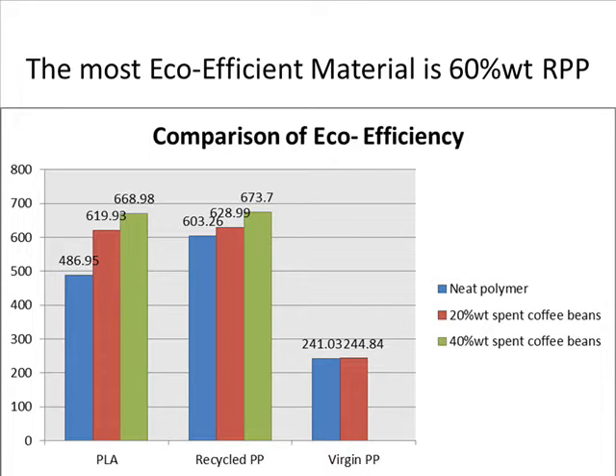However, with a compromise in the tensile and impact strength of the materials, although polylactic acid has better mechanical properties than recycled polypropylene, its carbon footprint is higher, resulting in the eco-efficiency of the bio-composite compounded with 60% by polylactic acid and 40% by spent coffee beans being slightly lower than the bio-composite made from 60% of recycled polypropylene and 40% of spent coffee beans. Nevertheless, as the life cycle inventory of the polymers was only considered from cradle to gate, the results might differ if the scope were to extend and include usage and disposal. Therefore, polylactic acid, being degradable, may be able to induce lower impacts at its end of life compared to that of the recycled polypropylene.